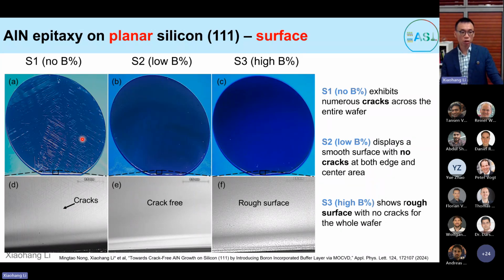The first sample, without boron, has a tremendous amount of cracks that are visible to the eye. For the second and third samples, we realize a crack-free surface. But we noticed that sample 3, with the highest boron flow, has a very rough surface here, which is consistent with the in situ monitoring.